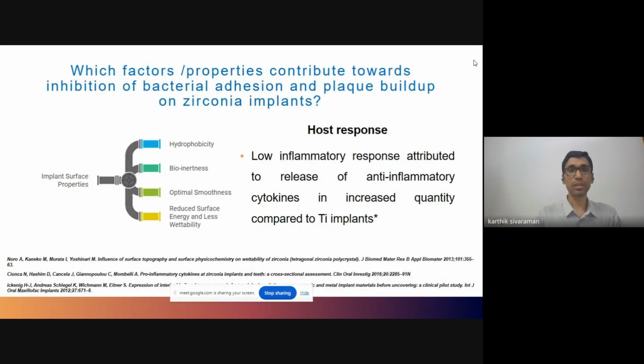peri-implantitis. So what are the factors or properties which contribute towards this inhibition of bacterial adhesion and plaque buildup on zirconia implants? So they include a range of factors which can be divided into implant surface properties and host response. So the relative bioinertness along with reduced surface energy is supposed to be a major property of the implant surface in zirconia, which inhibits the buildup of bacterial adhesion and plaque buildup.